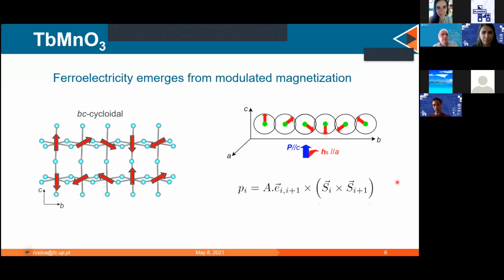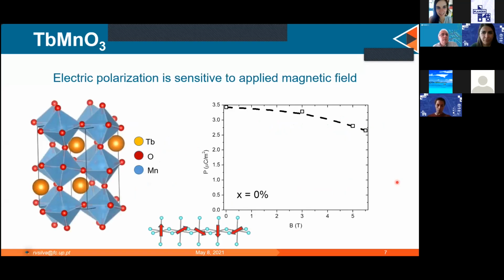So because the ferroelectricity comes from the magnetic ordering, they are inherently coupled, and now you have a multiferroic that is also magnetoelectric, which you can control in a cross-coupled way. So just to show you a few results on terbium manganite, which is actually very well studied by many groups, you see that it has a ferroelectric polarization, and it changes as a magnetic field is applied. But the way it changes is not so strong as one might expect.